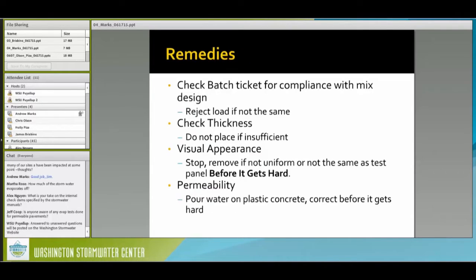Your check and balance in the specification: once you have an approved mix design, it will become part of the specification and the expectations for the project. Every load of concrete delivered to the site will come with a batch ticket, and you'll be able to check the proportions for compliance with the mix design. It should also carry the same identifying number as the submitted mix design. If that batch ticket isn't right, you don't need to discharge any of the concrete — send it back before any of it ever gets on the ground.